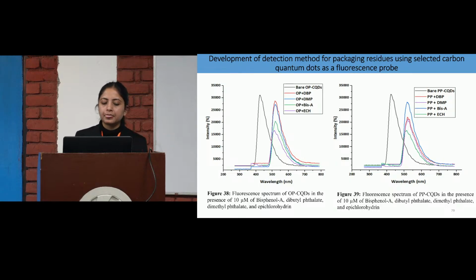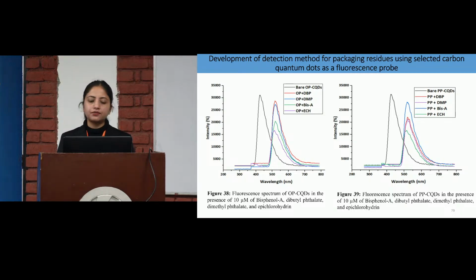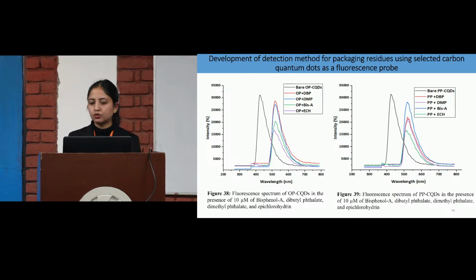Firstly, what we did there was check the fluorescence spectra of the onion peel derived carbon dots in the presence of 10 micromolar bisphenol A, dimethyl phthalate, and epichlorohydrin. We dissolved it into the synthesized carbon dots, and then we checked the fluorescence intensity and change in the wavelength. So this peak is the bare one, meaning without the addition of any residue. This is the bare onion peel derived carbon quantum dots. When we add 10 micromolar of the bisphenol or other residue, they shift their wavelength towards the higher range.